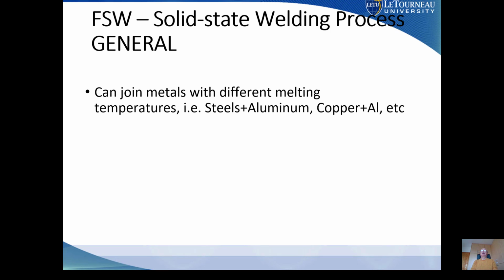temperatures. People have been trying to weld steel to aluminum for a long time, but obviously, because of the big differences in melting point, aluminum usually vaporizes before steel even melts. Similarly, copper has higher melting point than aluminum. So, needless to say, friction welding has been one of the best techniques to join dissimilar materials in the past. Simply friction, rotational. The friction stir welding has been done on dissimilar materials only after it was developed originally for aluminum lithium alloys.